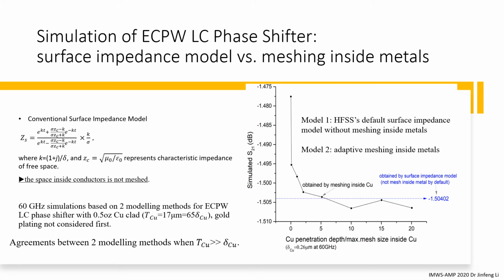We perform a 60 GHz simulation for the liquid crystal-based ECPW with the copper thickness of 17 microns, which is 65 times the skin depth of copper. Gold plating is not considered first. A comparative study on insertion loss calculation is conducted based on two models. Model 1 is based on the HFSS default surface impedance model without meshing inside metals. Model 2 is adaptive meshing inside metals and solving the internal fields of metals, refining the volume and surface meshes where the field gradients are high.